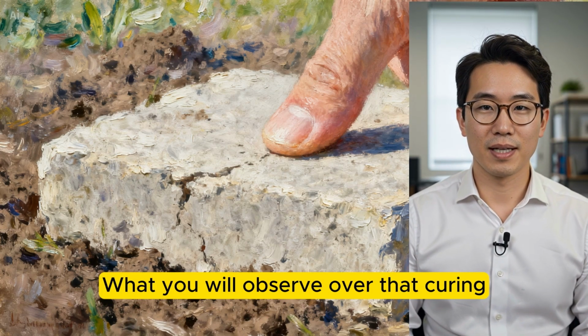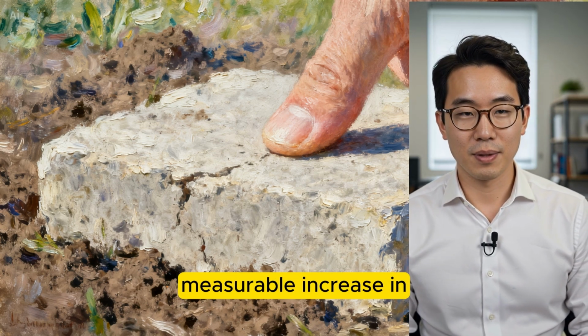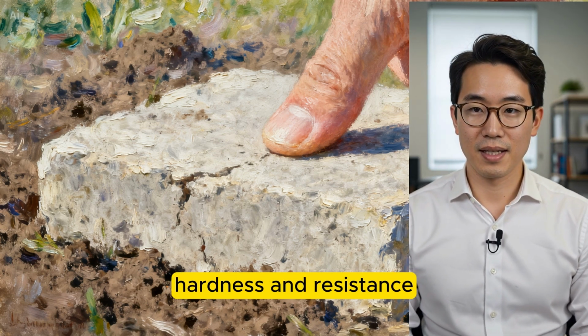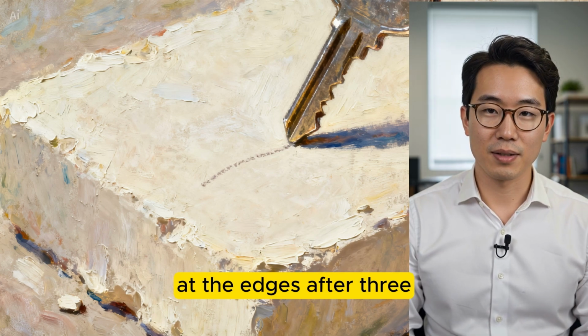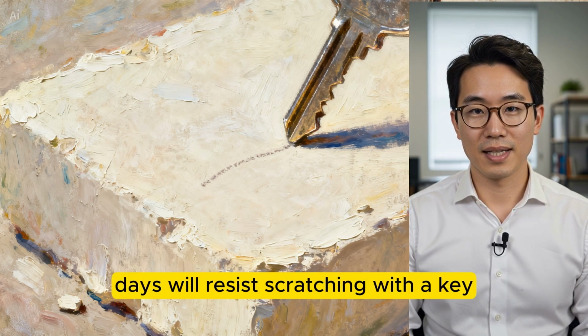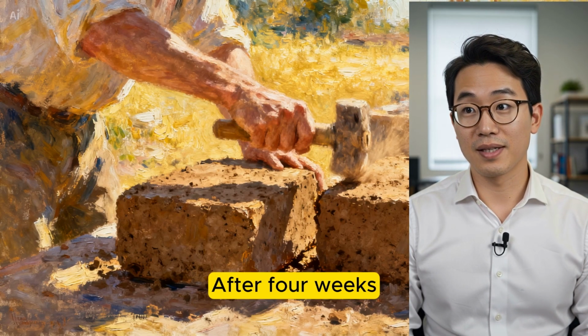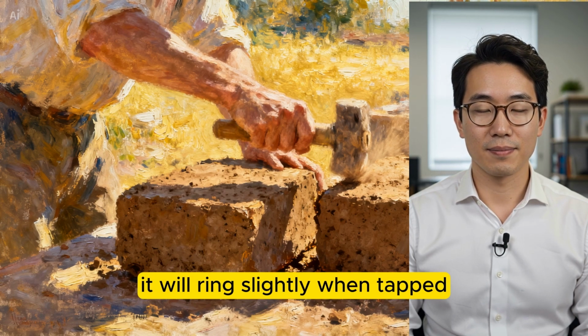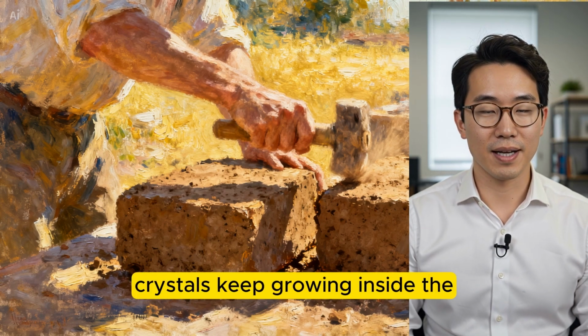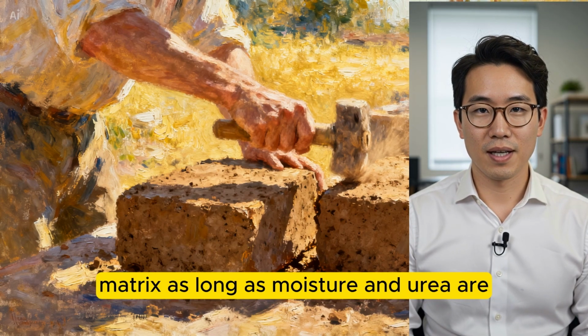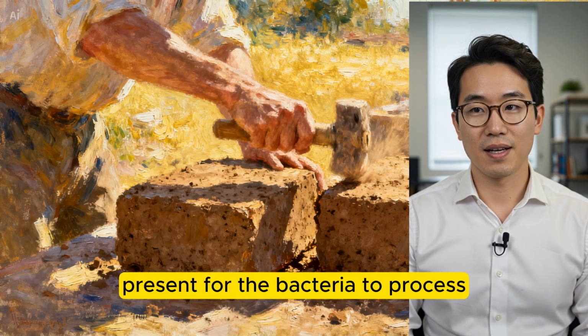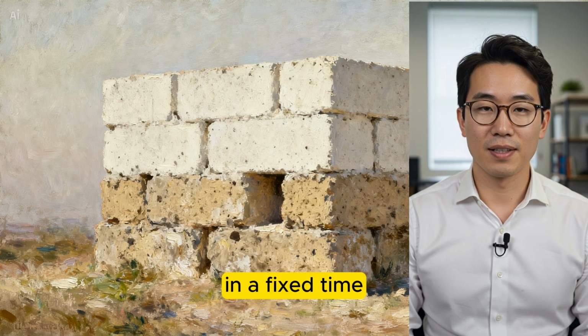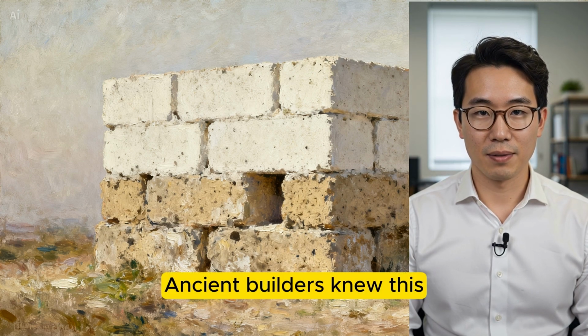What you will observe over that curing period is a gradual but measurable increase in hardness and resistance. A block that crumbles at the edges after 3 days will resist scratching with a key after 2 weeks. After 4 weeks, it will ring slightly when tapped. The calcium carbonate crystals keep growing inside the matrix as long as moisture and urea are present for the bacteria to process. The hardening is not complete in a fixed time. It is ongoing.